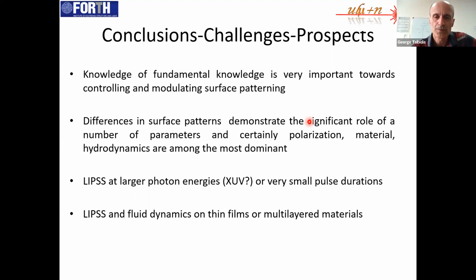And this is one of the reasons we want to couple our multiscale model with machine learning-based approaches, not only to facilitate, as I said earlier, the determination of the laser parameters to produce structures for certain applications, but also because we believe that through this scheme we will be able to reveal some unexplored physics, to identify parameters that play a more important role. It is also interesting to see whether we can produce periodic surface structures, some complex biomimetic topographies, for very big photon energies, so if we work in the XUV regime or with very short pulse durations.